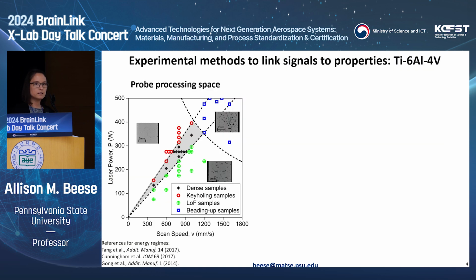Okay, so the way that we've done this is that we've taken a look at the knobs that we can tune in powder bed fusion, and we've fabricated components in different regions of this process space. So this is a plot of laser power versus scan speed, and the different symbols represent different types of regions that we might be processing in with laser powder bed fusion. Specifically, red would be if we have keyhole mode processing. Blue would be if we enter into balling-up thermal conditions. Green is lack of fusion type conditions, and then black and gray would be dense. And the idea here is that we would not intentionally process in these different regimes, but depending on the design of our component, we may enter one of these thermal conditions. So we want to understand, are there things that we can do during the process that we could recognize that we've gone into one of these regions?